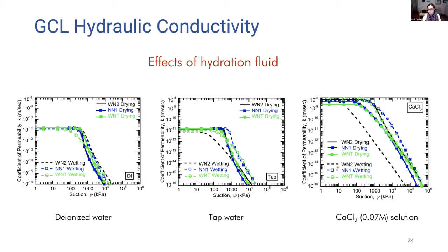For the calcium chloride solution, we observed that the starting coefficient of permeability is much higher. Now we have a three order of magnitude difference, from 10 to the minus 11, we moved up to 10 to the minus 8. This material also has a relatively uniform hydraulic conductivity for a while and then starts decreasing after, again, approximately the air entry suction for these products. We expect this kind of behavior in terms of higher values associated with saturated conditions and then decreasing hydraulic conductivity with increasing suction. This is the main reason why we conduct regular hydraulic conductivity tests in the laboratory under saturated conditions to arrive at the maximum hydraulic conductivity, and to be on the conservative side. And we see that over here.